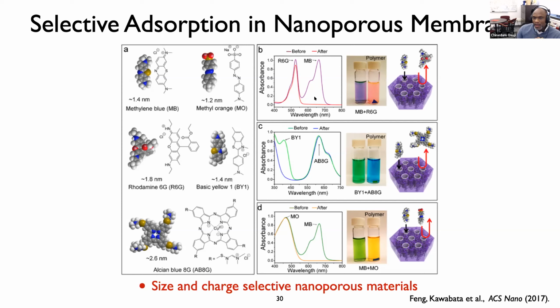So for example, here we have an aqueous solution that contained rhodamine 6G. It's a red dye, it absorbs in the blue. And methylene blue, it's a blue dye, it absorbs in the red. The combination is purple. After we introduce our polymer containing these aligned nanopores, the blue dye goes into the polymer while the red dye stays out. And the reason is that there's a roughly 0.4 nanometer difference in the effective van der Waals diameter, if you will, of rhodamine 6G versus methylene blue.